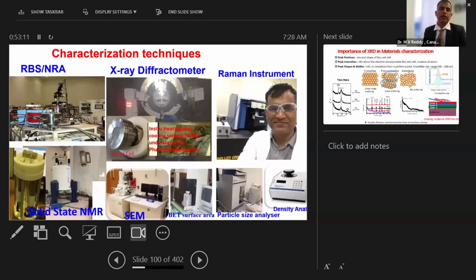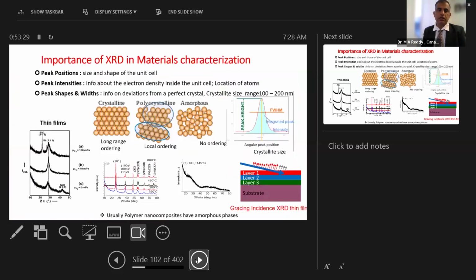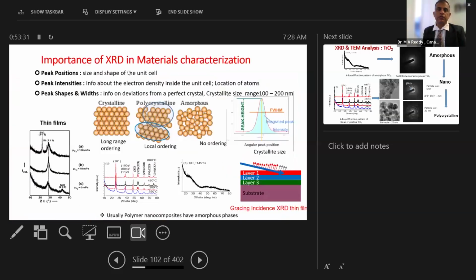Why I'm mentioning that: when I was working more than 25 years back on XRD, with Rietveld refinement, a good data collection used to take more than 24 hours. Now, due to the advancement of technology, within 5 to 10 minutes we can collect the data clearly, thanks to instrumentation and detector technology. Now coming quickly to XRD, I think people have already touched on it, so I don't need to discuss too much detail.